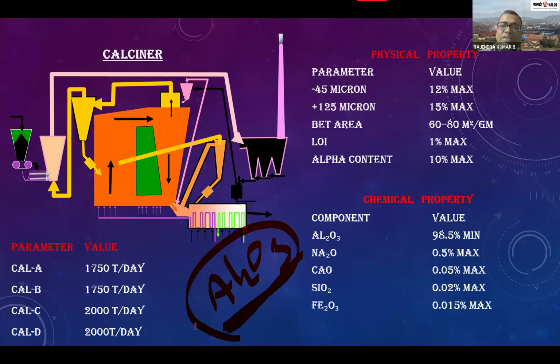The physical property value is minus 45 micron, 12% maximum, and plus 125 micron is 15%. Balance is in between them. Then alpha content is 10% maximum. Chemical component Al2O3 98%. This is the final product.